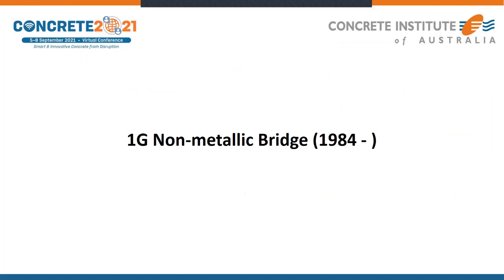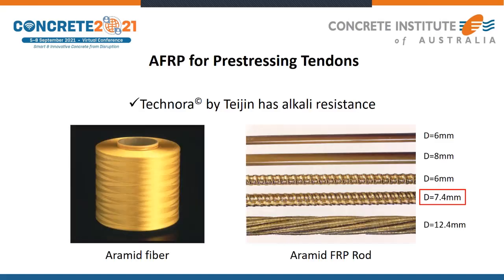This is the first generation of non-metallic bridge, started from the early 1980s. In the beginning, we used aramid fiber reinforced plastic tendons. At the time we also had carbon, but we chose this one because Technora by Teijin has alkali resistance. We tried a series of tendon types, but finally we chose a diameter of 7.4 millimeter, deformed type, because we need some bond stress with the concrete.